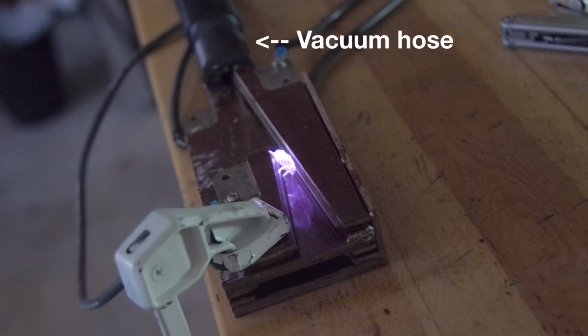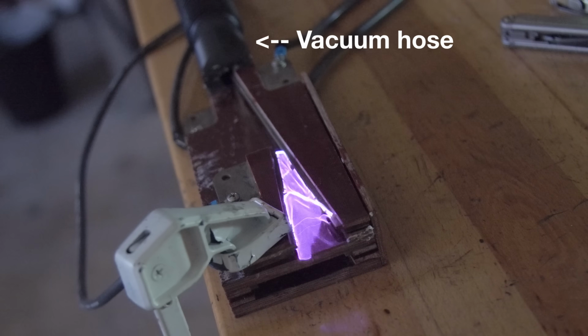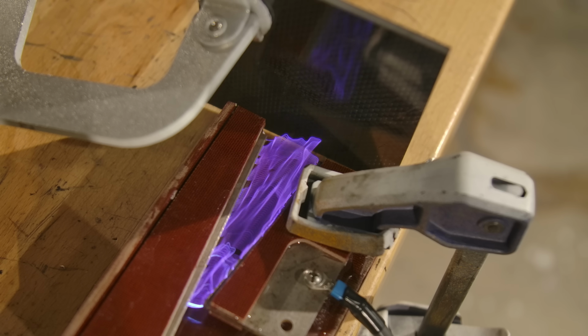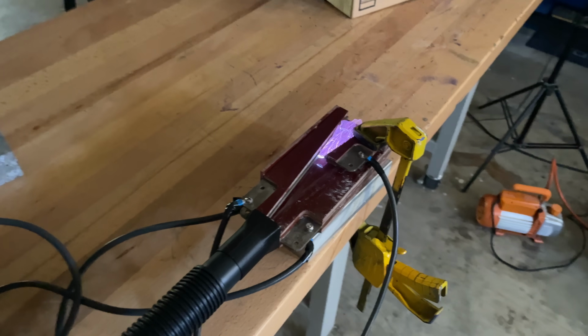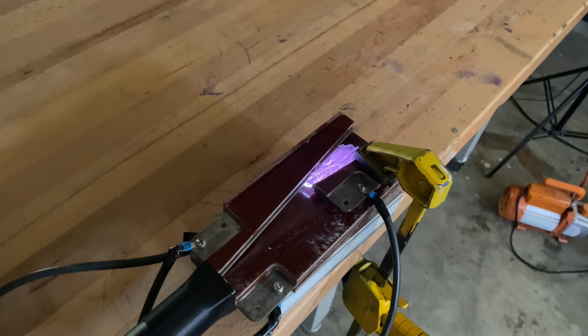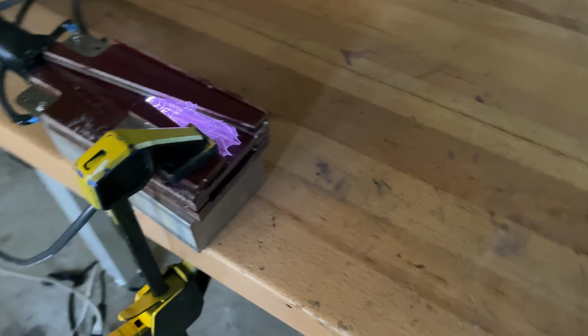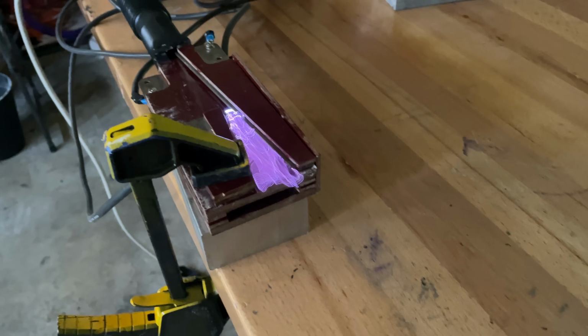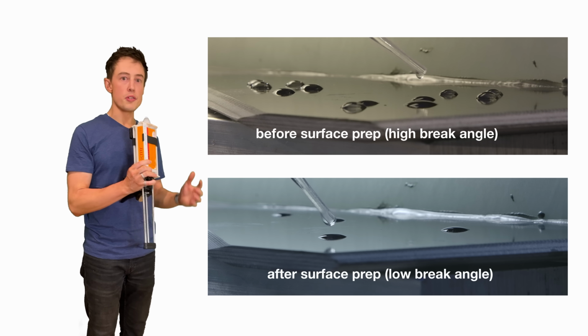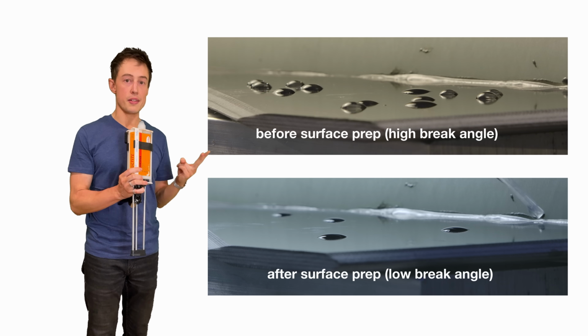Then, if we take a vacuum hose and hook it up to the outlet of a vacuum and blow air across that arc to force it down these long steel leads, we aren't just lengthening the plasma, we're making it last longer, and we're also blowing that atomic oxygen out the end of this gliding arc. This is called gliding arc discharge, and it kind of worked.